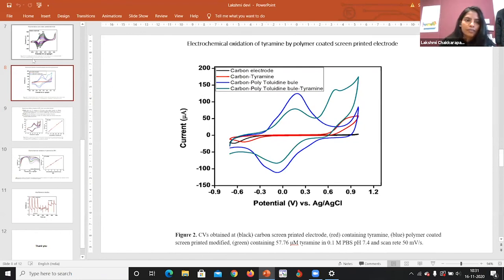So how did we get this stability? We used a cyclic voltammetry technique, and we took the modified electrode and used the phosphate buffer solution as electrolyte. We ran almost 100 cycles, and then we used this same electrode for the tyramine analysis and further studies. That's why we could say it has great stability. After the 100 cycles, it doesn't show a lower current response. The current is stable. So that's why we feel this electrode has high stability. Okay, thank you. You're welcome.